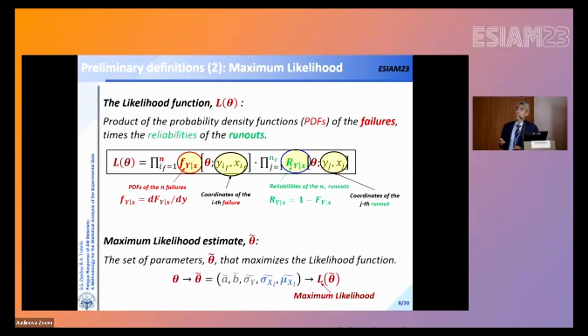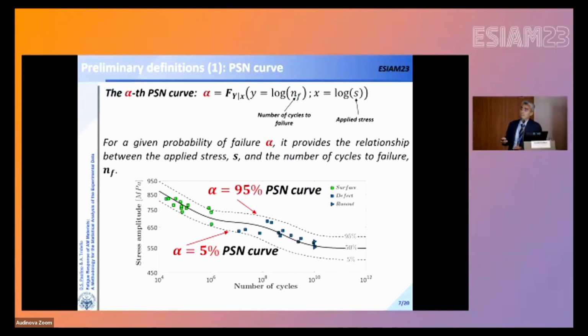And by definition, the likelihood function is the product of the probability density functions, which are the derivatives of the probability functions, for the set of failures, where y and x are the coordinates of the failure with subscript f, times the reliabilities, which are 1 minus the probability functions for the runout specimens. These couples are related to the coordinates of the runout specimens. Then by maximizing this function, which is just a function of the set of parameters that you want to estimate, in the case of linear with fatigue limit, 5 parameters, you can get the maximum likelihood estimate that must be put inside this equation to get the curve.